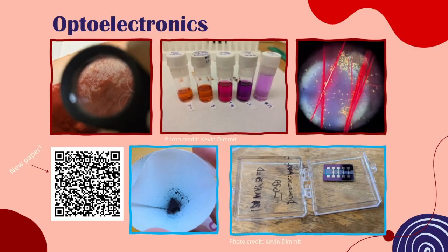on the viability of this. In the middle, we see a really good example of the pH dependence of the color. On the left, we have our pigment solution ranging from around 0 to 5 in pH, pretty acidic, and when we get to around 9 to 10, it turns to shades of purple, and eventually once it is at 12 or higher, it becomes entirely purple. This is really important because it affects the color of the resulting laser and the resulting device.